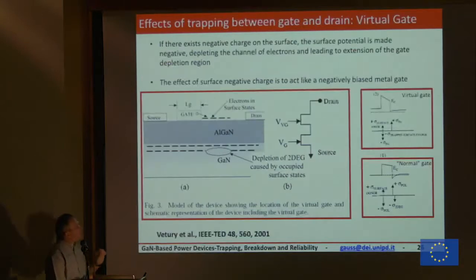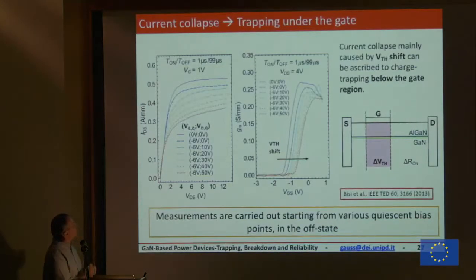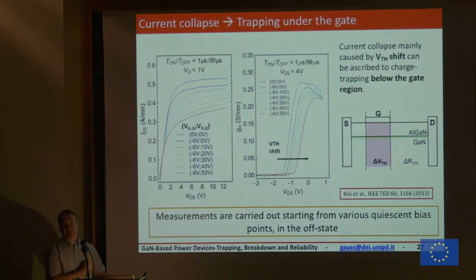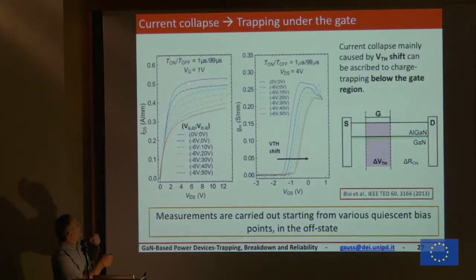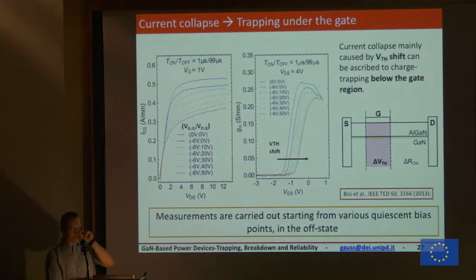A little better measurement that we can do is not measuring ID versus VDS, but just to do ID or GM versus VGS. Because this kind of plot provides you much better information. In this case, for instance, for this device, from this plot I cannot understand much, but from here I have a clear indication of what is going on. The current drop or the current collapse is due to a threshold voltage shift with a very low collapse in the transconductance peak.